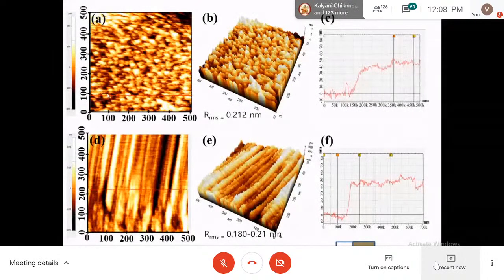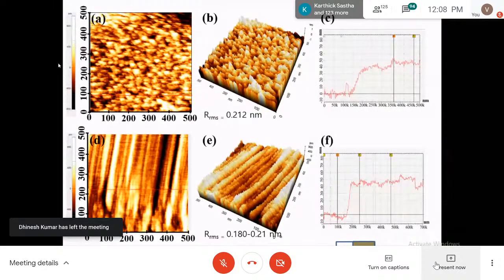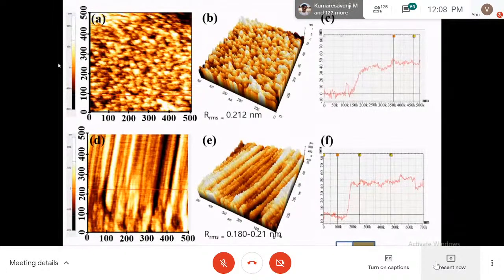The 7.5 minutes cyclohexane coated sample shows a root mean square roughness of around 0.2 nanometer. And then the bottom one, E, the 10 minutes cyclohexane coated sample, shows 0.18 to 0.21. That is a small decrease in the roughness. So the 7.5 minutes sample shows higher roughness than the 10 minutes coated sample.